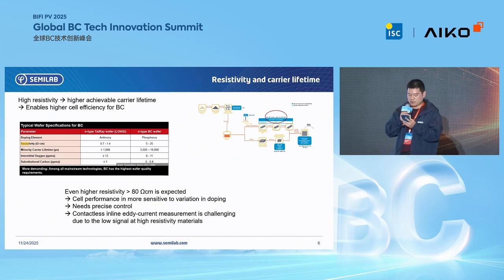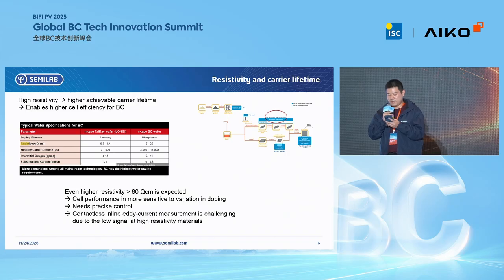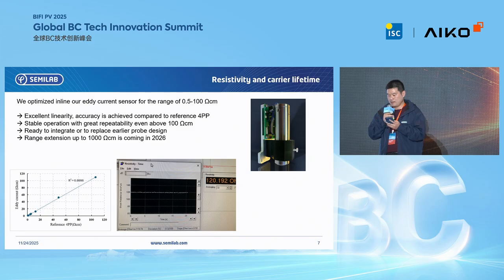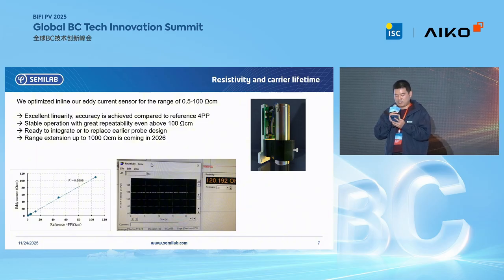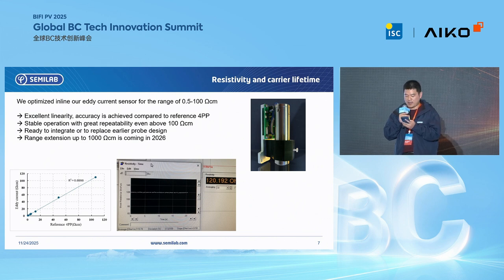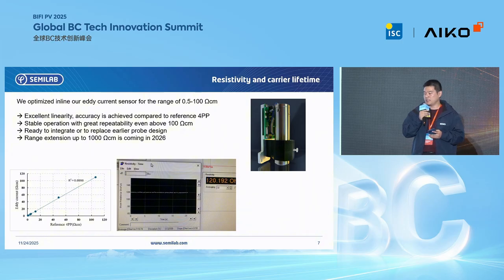Eddy current is one of the most widely used techniques for inline resistivity measurement, but its application in this high resistivity range is challenging due to the lower signal and the higher influence of environmental conditions. Our engineer this year optimized the probe parameters from 0.5 to 100 ohm centimeter. It maintained high linearity, I mean excellent correlation with the reference four-point probe within plus minus 3% accuracy, and it still has good repeatability even above 100 ohm centimeters. Another new type of sensor is developed and already tested. It extends the measurement range up to 1,000 ohm centimeter and will be commercially available next year.